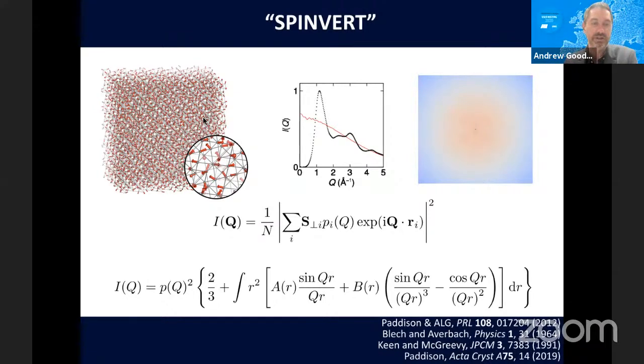Basically, you build a sort of supercell of your underlying structure, decorate it with lots of spins, and then you can calculate from this the scattering, be it either in powder form or in single crystal form. And then simply by moving the spins, you can try and fit those as well as you possibly can. The equations that do this have been in the literature for quite some time. This is a kind of progress that you might get with a powder fit, for example. You start with something that looks like the magnetic form factor and fit eventually.